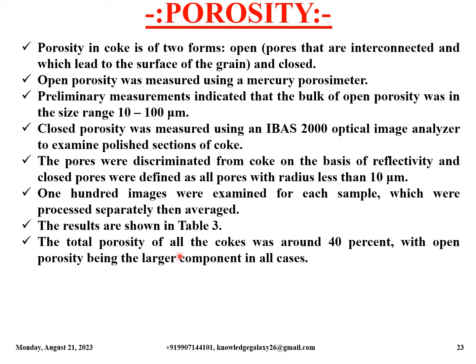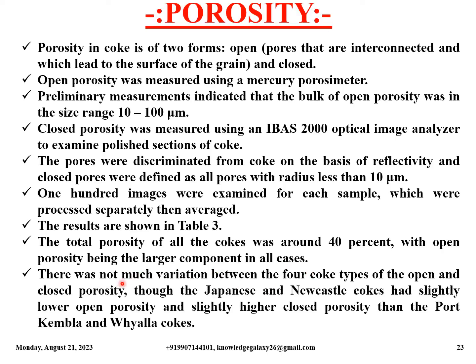The total porosity of all the cokes was around 40%, with open porosity being the larger component in all cases. There was not much variation between the four coke types in open and closed porosity, though the Japanese and Newcastle cokes had slightly lower open porosity and slightly higher closed porosity than the Port Kembla and Whyalla cokes.